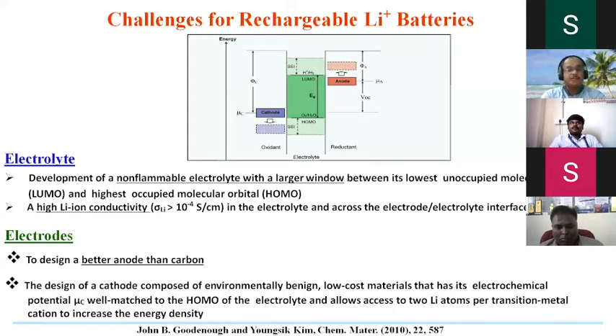This is regarding the electrolyte. For electrodes, we need to design a better anode than carbon or graphite. It's a very difficult task. People are struggling hard, moving towards silicon and other options. Still, it's going on. Nothing yet for a new anode. Then to design a cathode composed of environmentally benign, low-cost material that has its electrochemical potential well matched with the HOMO of the electrolyte and allows access to 2 lithium atoms per transition metal cation to increase the energy density. It looks very simple, but allowing 2 lithium atoms per transition metal cation is a tough job, so we have to look into new cathode materials. These are the challenges to realize really high energy density batteries.